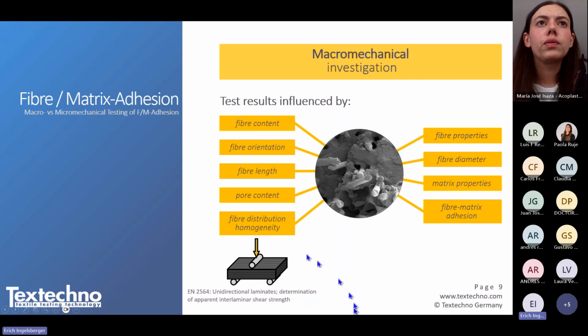Also the pore content, how many fibers, how many matrix in volume percent, the fiber distribution homogeneity. Of course, also the fiber properties, fiber diameter, this goes into the test results. Matrix properties certainly also, and fiber matrix adhesion, this is the property we like to measure. This also goes into the results, but there is a lot of risk of influence of uncontrollable or difficult to control parameters.